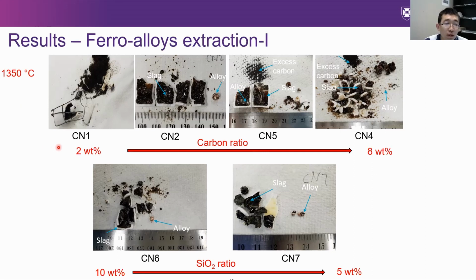that will vary the carbon from 2% to 8%. So basically, we got the alloy and then separated it from the slag. The slag at high temperature is in the molten state. However, when it is quenched in water, it cools very quickly and has no time to crystallize. Then it becomes a glass. So it's a very brittle glass here, the slag.